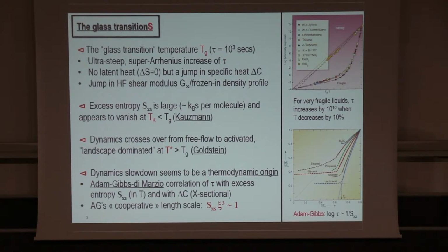And this entropy appears to vanish at a different temperature below Tg, which is called the Kauzmann temperature. And so here you see graphs of this entropy extrapolating to 0 below the glass temperature. The dynamics seems to cross over from an essentially unencumbered flow at high temperature to something that becomes activated, or as Goldstein called it, landscape dominated. And this appears at another temperature, T star, above Tg.